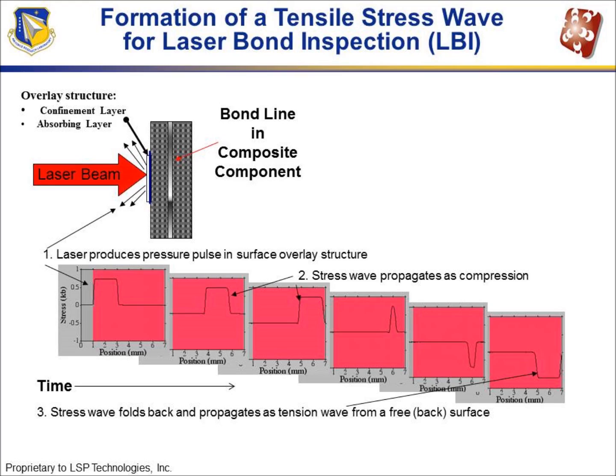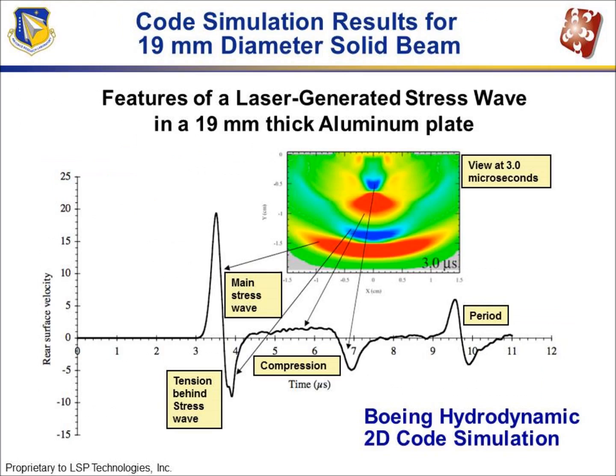This is a code simulation that results from a 19 millimeter diameter solid beam that is interrogating a 19 millimeter thick aluminum plate. In this particular case, since the beam diameter is about the same thickness as the aluminum plate, the stress waves that are produced are much more complicated. It's just not made up of a single compressive wave moving forward, but actually has compressive and tensile waves moving forward. The complication exists because of the edge effects on the beam finite dimensions, but this shows exactly what happens at the back surface.